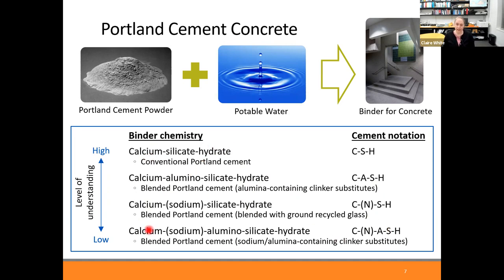And if we continue going on with other elements, sodium, for example, you can get the CSH gel with sodium in it. And then also when you have sodium and aluminium, you get this CNASH gel. So we really need to understand what impact the additional elements have on the structure of this gel, and also how the thermodynamics of the gel changes. And it's very hard to analyze this gel within the concrete system because of all of those other phases that exist. So what I'm going to show today is some computational chemistry research we've done on just the gel itself to give us some information on the thermodynamics, and also some experimental results that we've discovered for these systems.